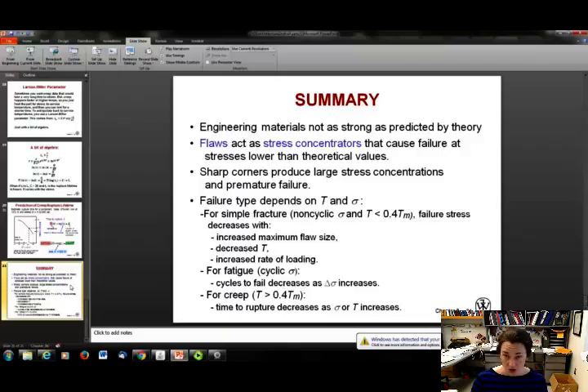If you have a sharp corner in your part, you definitely want to get rid of that. You don't want that included in your design because that's a large stress concentration right there that can help out with premature failure, which is totally undesirable. Your failure type is going to depend upon your temperature and your stress, okay? If you have a simple fracture, where your stress is non-cyclic, and your temperatures are relatively low, then your failure stress is going to decrease with increased maximum flaw size, decreased temperature, and increased rate of loading.